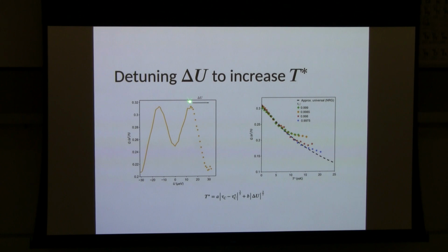We can pick a point in this parameter space of gate voltages where we think we're completely at a quantum critical point, or very, very close to it, and then we can move away from that by tuning gate voltages. And there's a scaling theory for how tuning away in gate voltage should change the effective energy scale below which we see that the symmetry is broken.